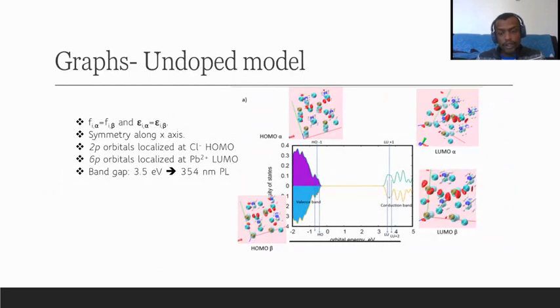So for the undoped model, as we expected, there are very similar density of states plots. Here we can see the alpha at the top, and then beta spin orbitals at the bottom, with the valence band at the left and the conduction band at the right. And also we can see from the pictures of the orbitals, the orbitals localized at the chlorine ion, and then at the lead ion for the LUMO orbital. Here the band gap was measured to be around 3.5 electron volts, which would correspond to an emission of around 354 nanometers, which is close to the experimental graph that I showed in the introduction, and that's around 400 nanometers. Next slide, please.